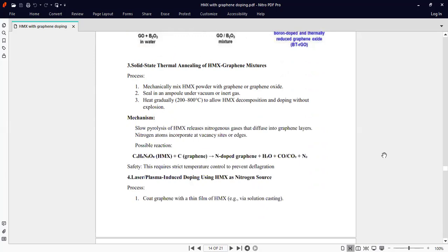The third method is solid-state thermal annealing of an HMX graphene mixture. Mechanically mix HMX powder with graphene or graphene oxide, and seal in an ampoule under vacuum or inert gas. Heat gradually to allow HMX decomposition and doping without explosion. The mechanism of this type is slow pyrolysis of HMX, releasing nitrogenous gases that diffuse into graphene layers. Nitrogen atoms incorporate at vacancy sites or edges.